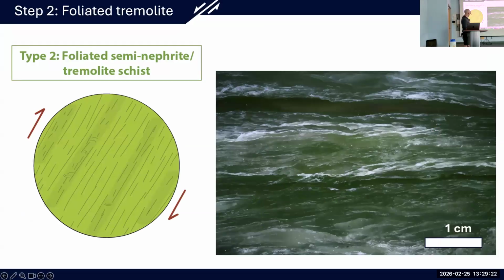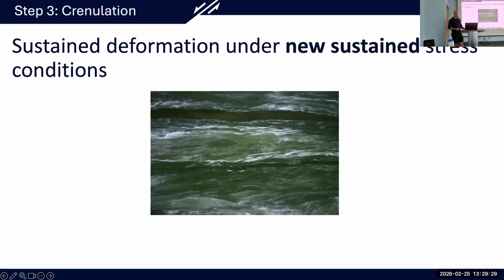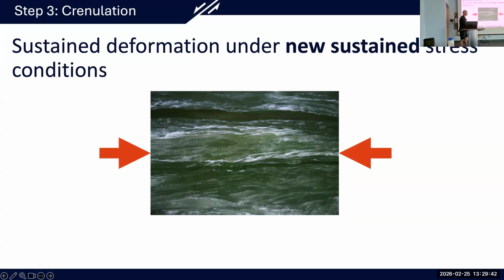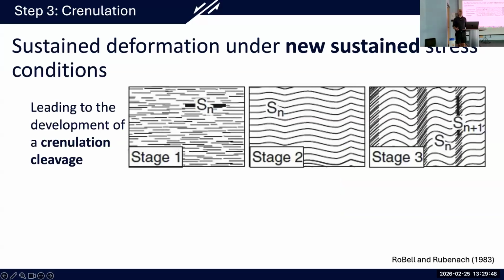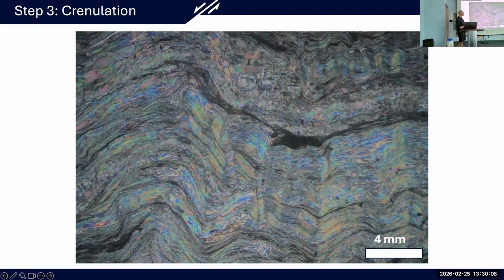We take our foliated tremolite schist, some might call this a semi-nephrite, and we sustain deformation under new stress conditions, evolving stress conditions. So perhaps within that shear zone, things have shifted slightly, and there's a new dominant force. So in this case, we're going to imagine that we're going to compress our foliation at 90 degrees to that original orientation. And this is going to develop what we call a crenulation. The same process of grain reorganization by pressure solution is now going to take action, but with our compressive stress against the long axis of those needles. And so essentially that will end up folding and buckling our tremolite.